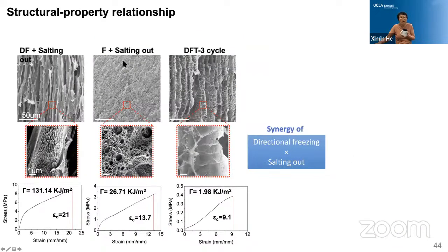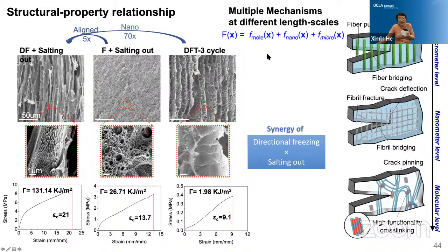And then overall, we compared this tough gel with 2 control samples, which omit this directionality during the freezing. So it's a homogeneously frozen sample followed by salting. And then we saw that missing the aligned microstructure, the mechanical property, like the strength, is about 5 times lower. But if you omit the salting-out step, with only the freezing step, even for 3 cycles, you create a gel with mechanical properties 70 times lower than this model material. This tells us, indeed, the unification of all these features at different length scales together produces this high toughness, high stretchability, and overall good mechanical property. So this really emphasizes this synergy between the directional freezing and salting out.